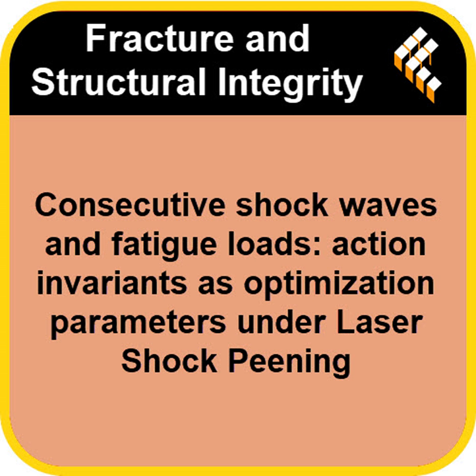Why polish it? Wouldn't that remove some of the treated layer? They were careful to only remove the very top surface roughness that the laser process itself can create. Those tiny ridges and valleys can act as stress concentrators, becoming initiation points for fatigue cracks, which masks the real benefit from the shock-induced changes within the material. So they wanted to isolate the effect of the subsurface compression and that changed microstructure, not just the surface topography. Exactly. Preserve the hardened layer, remove the potentially detrimental surface features. Smart.